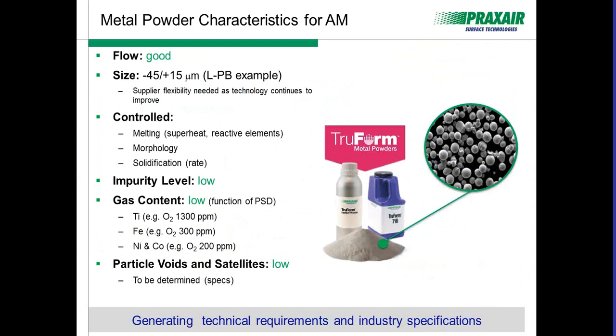The next feature is, how do we control this? How do we control the chemistry when we melt? Do we understand what temperature we need to raise the melt pool to, in order to get very good control over the pourability or fluidity of that liquid to feed it through an engineered nozzle? We also have to understand reactive elements. If we superheat too much, are we going to drive off certain reactive elements and therefore have too great a batch-to-batch variability for our customers to achieve repeatable results when they print this powder?